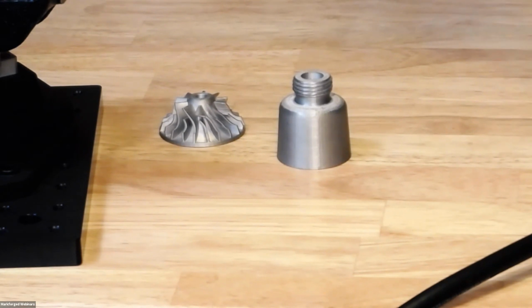Let's see. Someone asked about the hardness of H13 on the Rockwell C scale. So as printed, it's 40. If you heat treat, at fresh quenched, it's 50. Tempered to 600 degrees Celsius, it's 45. And if you temper it to 530, although we have not formally released this as data, I believe you can probably push up into the 50 range.